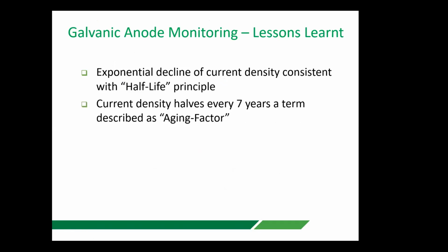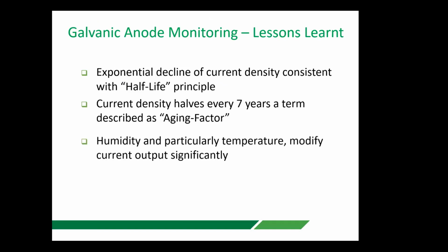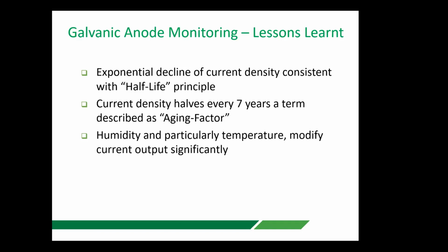Now, what else did we learn? The current density on this occasion halved every 7 years, and we term that the aging factor. So you obviously want to be achieving a higher aging factor than 7 years. Humidity and particularly temperature modify the current output significantly. And you would have noticed that the current was not totally exponential, but it went up and down depending on whether it was summer or winter.